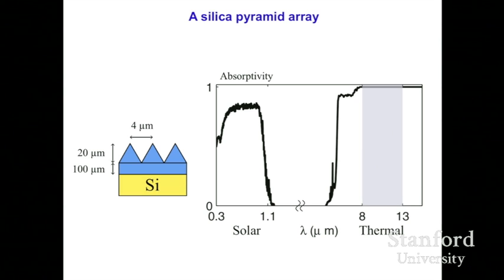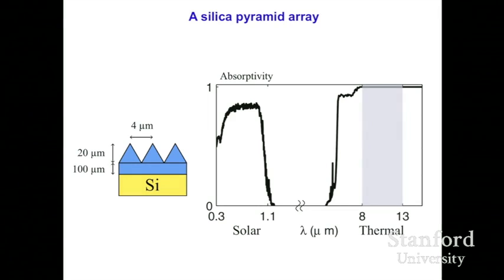In doing so, one does not affect, again, the absorptivity on the solar side. In fact, it slightly enhances the absorptivity because of some of the light trapping effect of the silica layer, but you can bring the emissivity of the structure to be near unity in the 8 to 13 micron window. So these are some of the theoretical simulations.